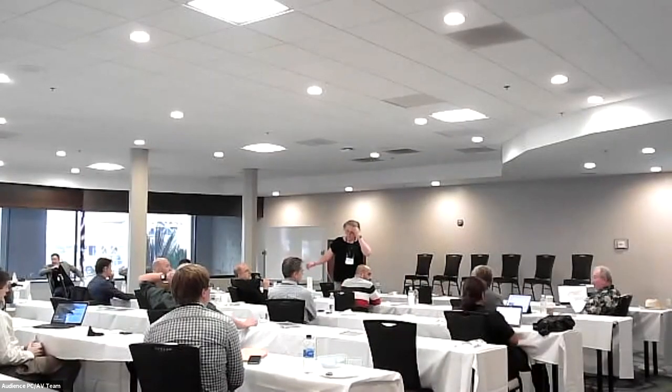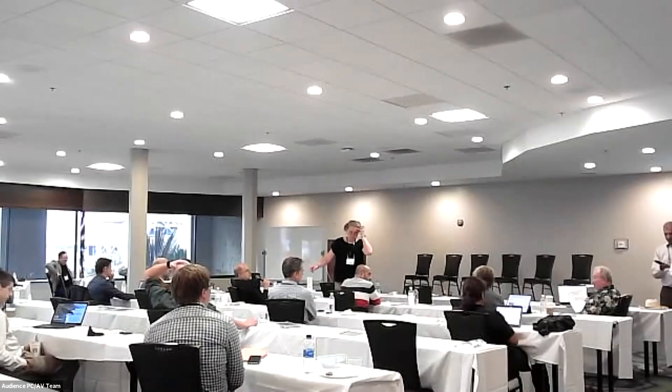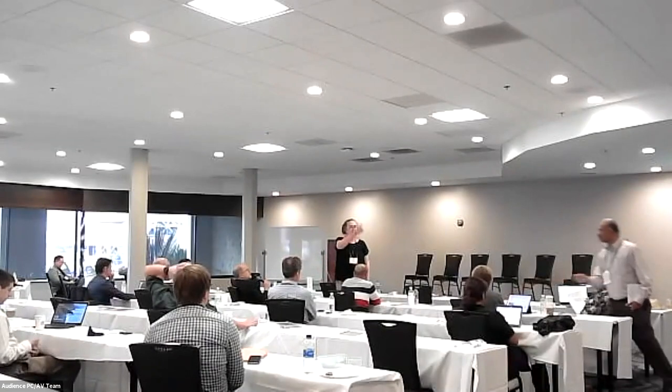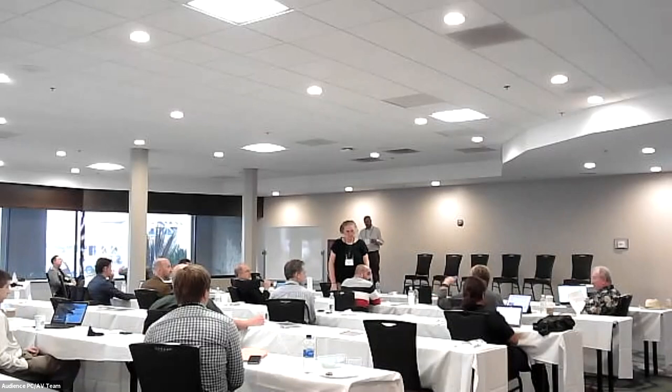Susan's question about the solubility maybe could be addressed by changing the chemistry of the water phase. They just didn't think about it for oil and gas applications. Susan, is there anything we could do to slow down the solubility, add salt to it? And if you chemically treat it, there's no telling how long it's going to stay in that solution and dissolve, go somewhere else. That's the problem. At really high temperatures, silica doesn't dissolve as well. If you get up above, I think it's like 550 F, it becomes less soluble. So it's got retrograde solubility.